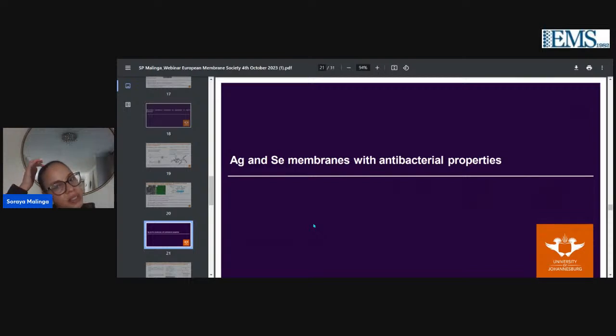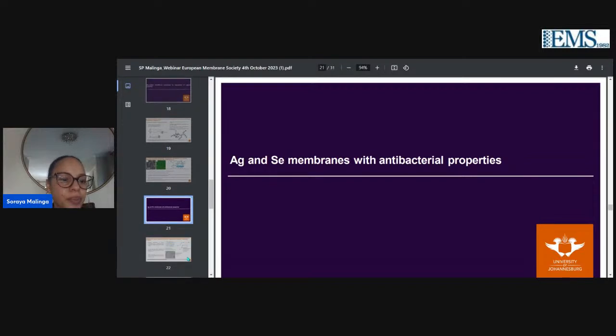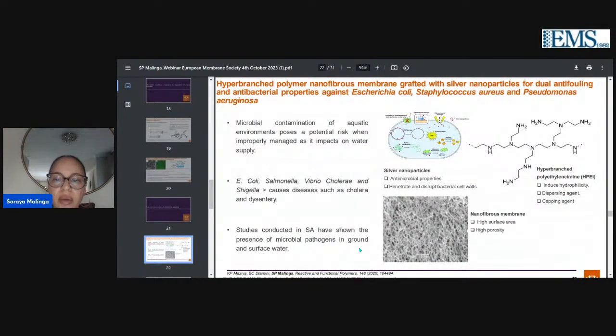Then for antibacterial properties, we've only explored silver and selenium. The same with silver, we opted to use nanofibrous membranes where we prepared the silver within the membrane. So it was an in situ kind of preparation. So in our casting solution, as I showed in the other slide where we have our syringe, we had our polymer of choice, PS, the solvent, and the silver. In this case, we use silver nitrate.